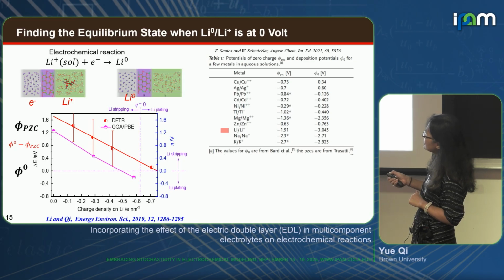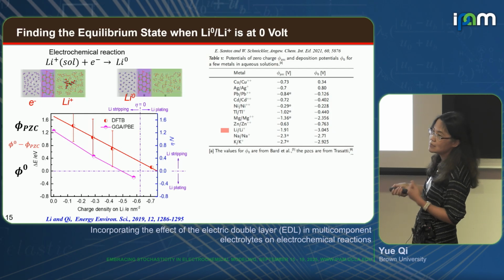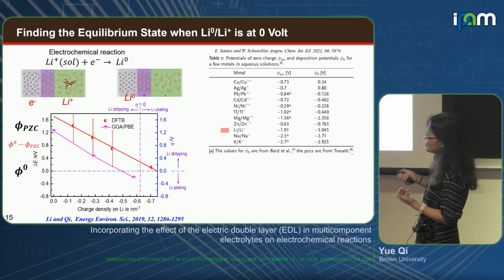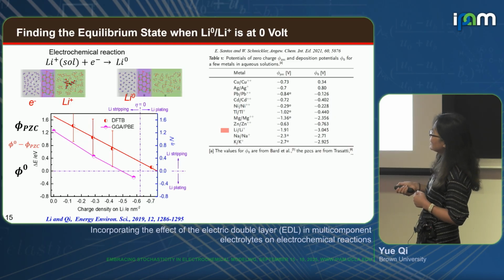So eventually we built this cell with about 1,000 atoms, like lithium, a passivation layer, and some 32 EC molecules, and then we look at the energy difference of the ion when the ion stays in the lithium metal. We look at the energy difference of that, and then the more ions we put in the electrolyte, the more electrons we left on the lithium metal. Eventually, we can see the electrochemical equilibrium condition and how much charge density I have to have on this lithium metal. This will simplify my other calculations later, right? I would need to calculate the double layer, and I need to know the potential minus the potential of zero charge.